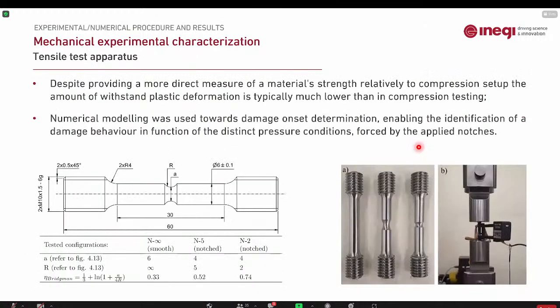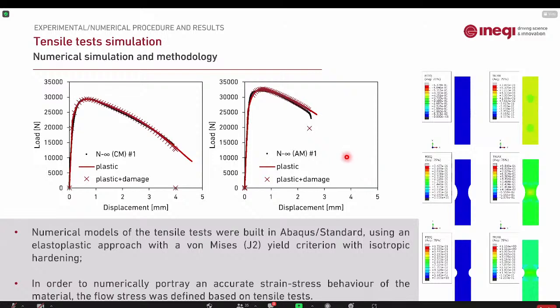We also did tensile tests. These were done for different stress triaxialities with different notches. We obtained the fracture strain through simulation, through fitting of the curves and determining plastic and damage response.